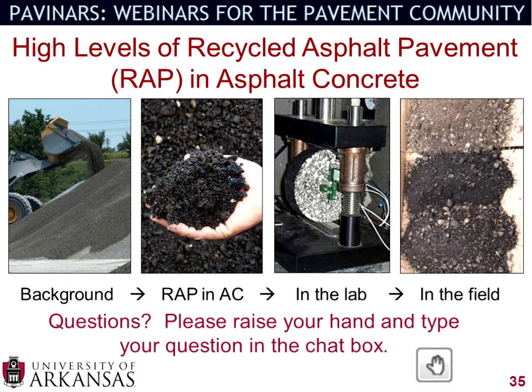Oh, and then Irv Ducats, thank you, Irv, for pitching in. He says that the BR, the blending ratio, gives a better description of the actual amount of binder coming from a particular RAP source. That's a very good comment, Irv, and I agree 100%, because if you're assuming 20% RAP by weight of aggregate, you do not know how much of the binder of that RAP is actually being used and activated and replacing virgin asphalt cement. But if you're using your binder ratio, then you know exactly how much asphalt cement you're using.